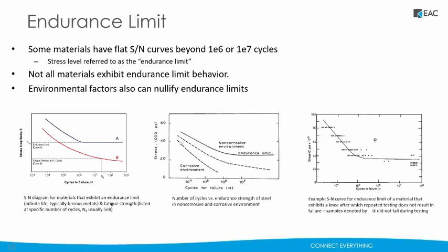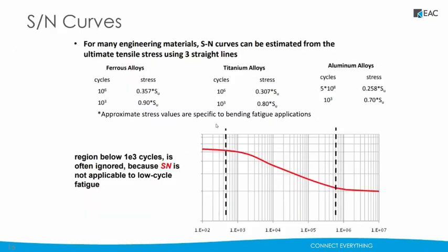In other environments, like a corrosive environment, or with some aluminum and other metals, there is no safe amount of stress. One always has to do a fatigue calculation because you can add up 10 to the 7 cycles pretty quickly if you're resonating at 50 hertz, maybe in a matter of weeks. So endurance limit isn't always something you can apply. Sometimes you can't just predict stresses and compare them to endurance limit. Sometimes you actually have to go the further step and predict fatigue life.